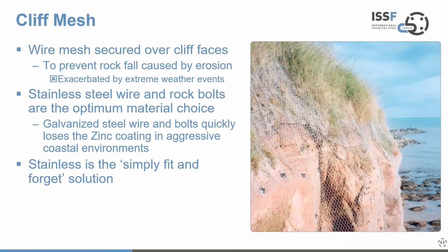One of the other areas we need to consider is cliff mesh, in order to protect some of our cliff faces, particularly with the erosion effects which are exacerbated by the extreme weather events we see now. Looking at wire mesh using stainless steel and rock bolts to secure those meshes in place becomes, again, the optimal choice, I would argue. You've got the same features going on if you choose a galvanized steel wire. You will lose the zinc coating, and even with epoxy coatings, the erosion will wear away the coating and you'll be left with a mesh that fails.